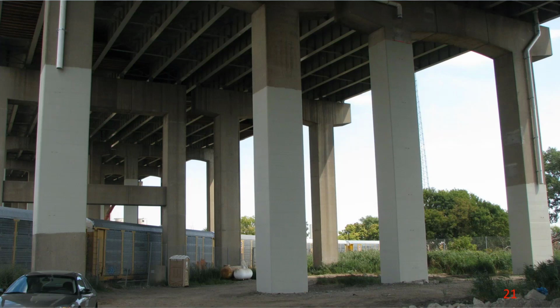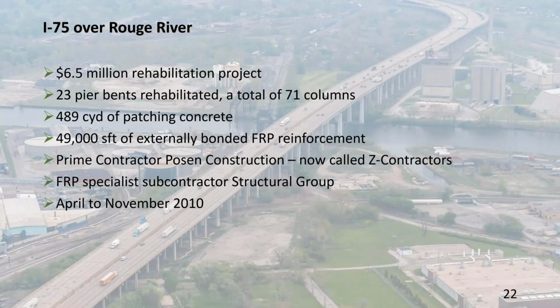As a summary, I guess, of the project, it was fairly large, but compared to replacement, not really. This project was about $6.5 million for everything, including 23 rehabilitated pier bents, or a total of 71 columns. Quite a bit of patching concrete was used for almost 500 cubic yards. 49,000 square feet of the FRP reinforcement was applied. And this was all done in one construction season.